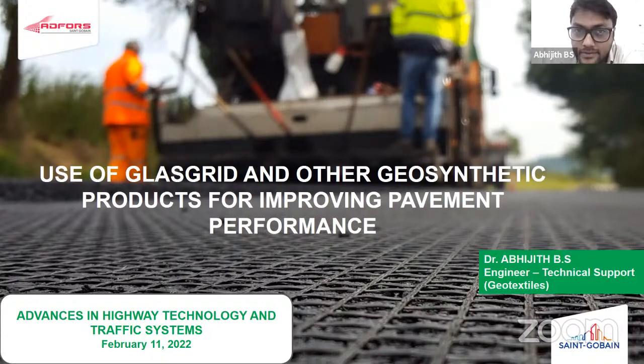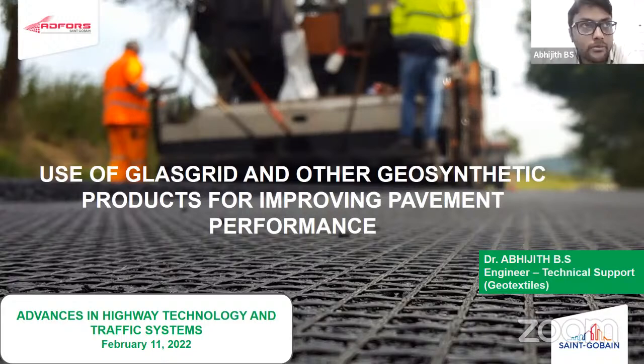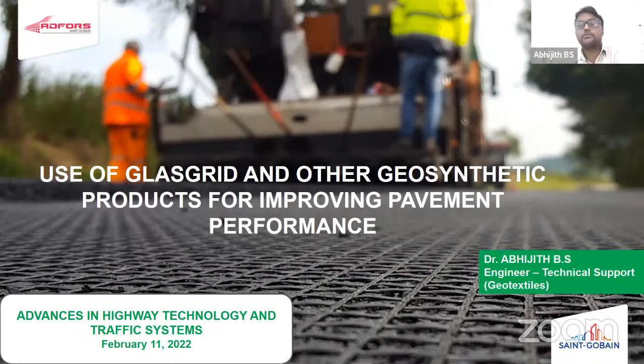Another question is, what is the thickness of GLASGRID? It will be up to 3 mm, in the range of 3 to 5 mm, for the composite glass. Another question is with respect to the design procedure, up to what thickness you have to lay this. The minimum thickness of asphalt mixture overlay on top of composite GLASGRID shall be 40 mm.